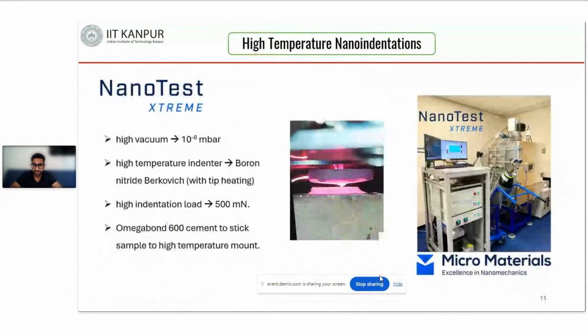Coming to high temperature nanoindentation testing, there is complexity involved. If you test at high temperature, there is a chance that the specimen gets oxidized, and even the indenter tip can react with the material, which deteriorates the properties of the indenter. Also, there can be a temperature difference between the tip of the indenter and the sample. That temperature gradient leads to thermal drift, which ultimately changes the measured value of hardness, so it can be inaccurate.